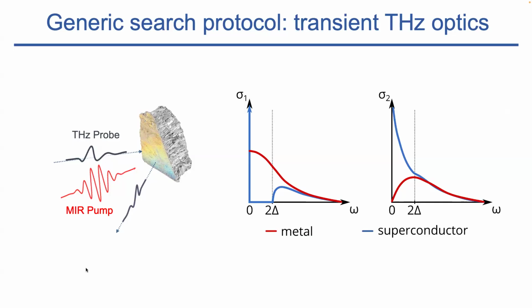And if you're above TC, you start from the optical properties of a metal, which look like so. These are the optical properties of a Drude metal here in red. You have a real part of the optical conductivity, which is the in-phase response of the current to an electric field, which has a finite value at zero frequency, and then it rolls down at the scattering rate. Apologies here, this is the gap, but there should be a scattering rate 1/tau here. And it has an imaginary conductivity, which is the response of the current which is in quadrature to the applied electric field, so the inductive response, which in the Drude has a peak at the scattering rate.